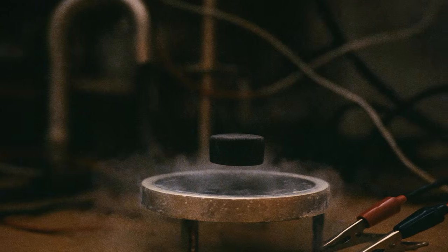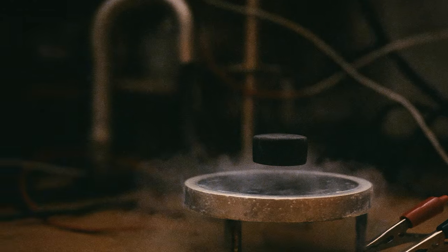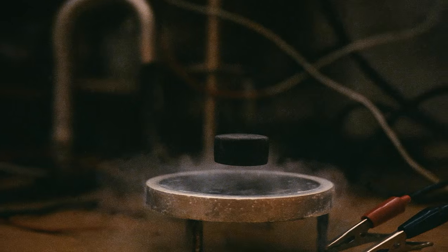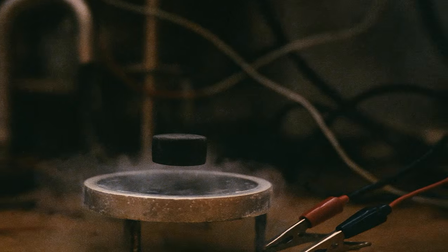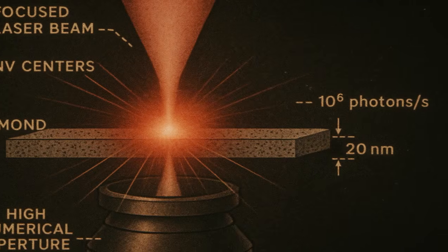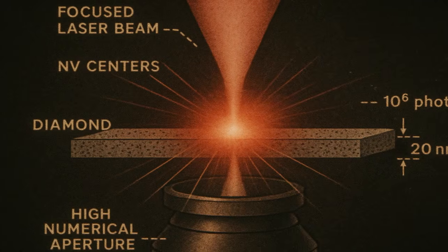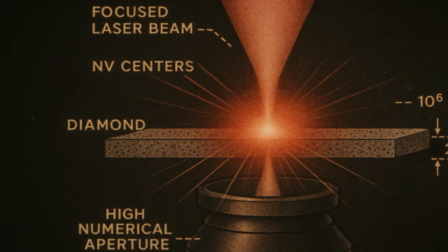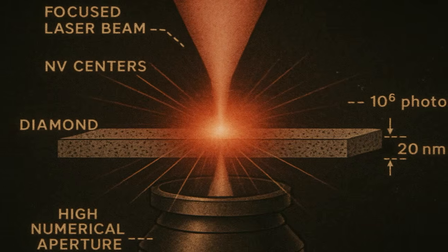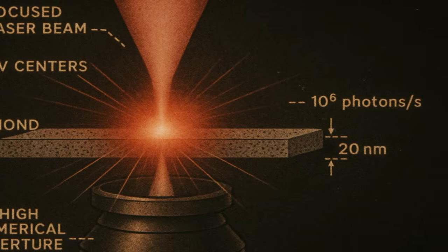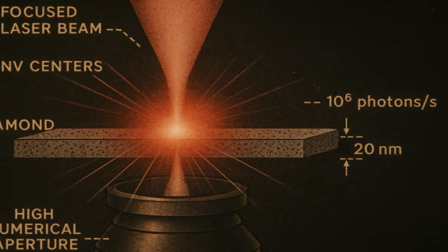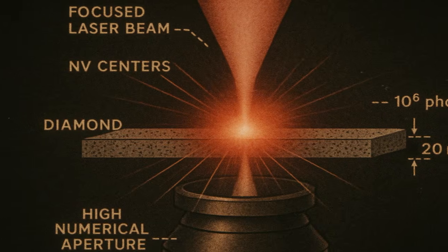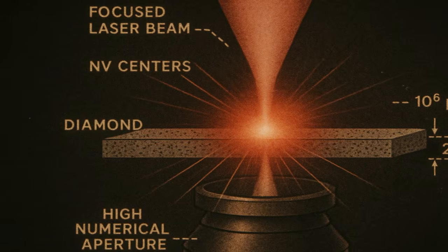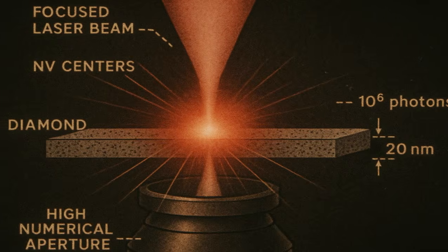The zero phonon line gets selectively enhanced if you tune the cavity mode to 637 nanometers. The phonon sideband doesn't couple to the cavity as strongly because it's off resonance. Result: sharper emission spectrum, faster photon rate, better collection efficiency. Researchers fabricated diamond microdisc resonators and got spontaneous emission rate enhancements of factor 10 for single NV centers, published in Nature Photonics in 2010. Ion implantation creates NV centers on demand.